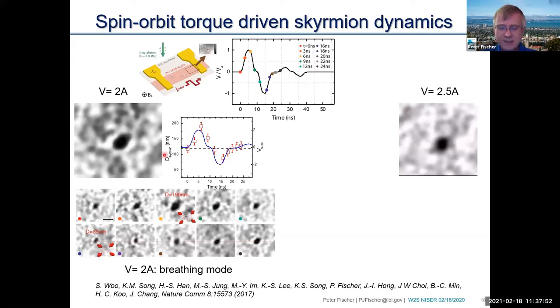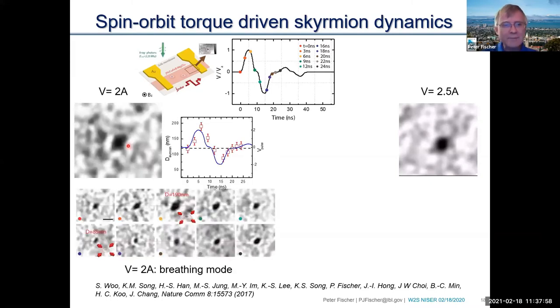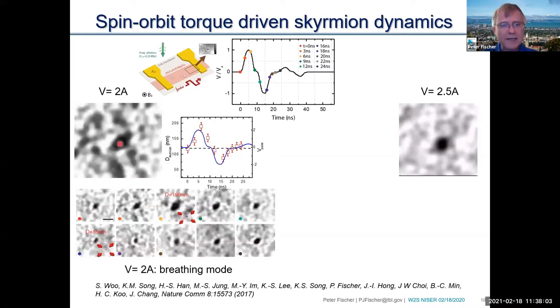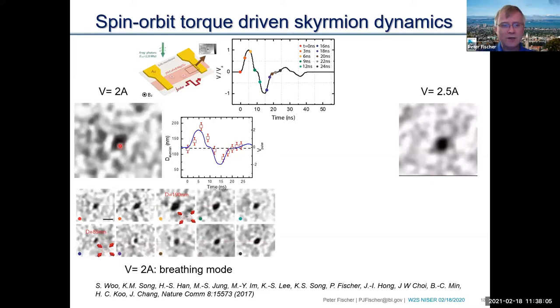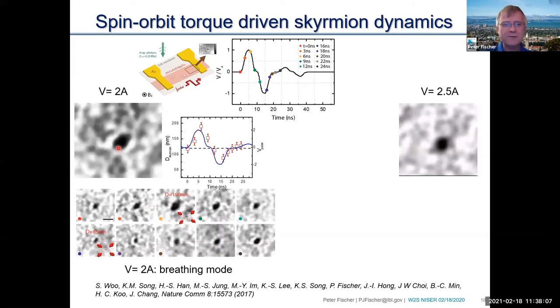And what you see, let me see if I can run this movie again. There we go. So you see now the dynamics that is going on in the skyrmion. And again, this is a 100 nanometer length scale roughly. And you see how it starts to really breathe up and down as a function of the time between the pump and the probe, right?